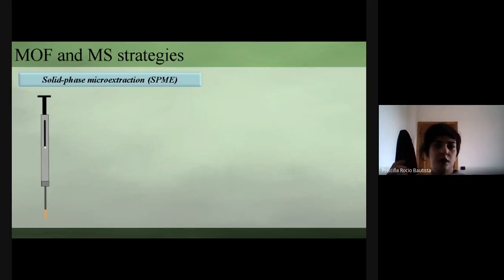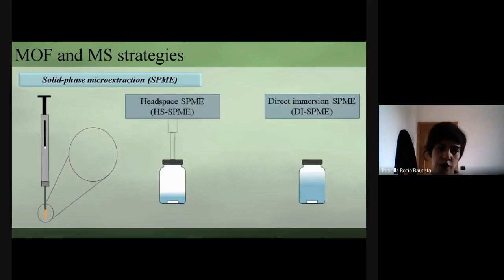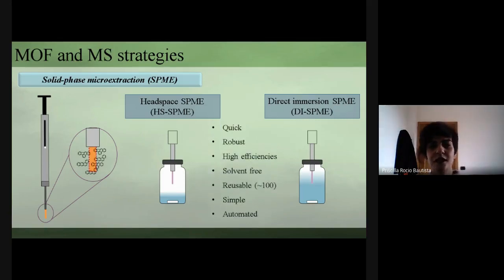One of the most extended coating devices based on MOF are fibers for solid phase microextraction schemes, which consist of an absorbent material supported onto a metal wire. These types of strategies are described in two modes: headspace, for the analysis of volatile and semi-volatile compounds, or direct immersion mode, where the SPME fiber is directly exposed to the sample. These techniques present a large number of advantages, but it's important to highlight the robustness and the reusability of the device.